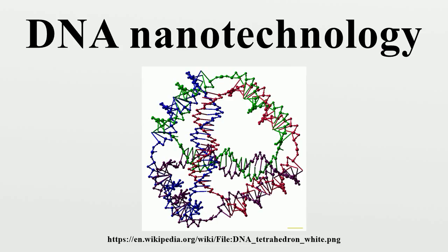Many of these schemes use a covalent attachment scheme, using oligonucleotides with amine or thiol functional groups as a chemical handle to bind the heteroelements. This covalent binding scheme has been used to arrange gold nanoparticles on a DX-based array, and to arrange streptavidin protein molecules into specific patterns on a DX array. A non-covalent hosting scheme using Dervan polyamides on a DX array was used to arrange streptavidin proteins in a specific pattern on a DX array.